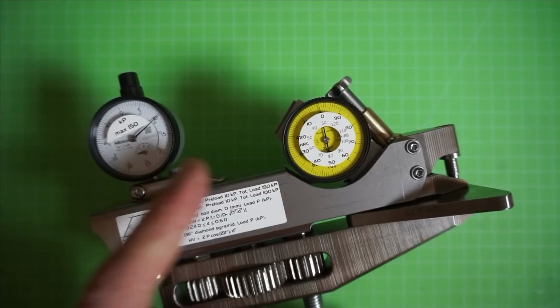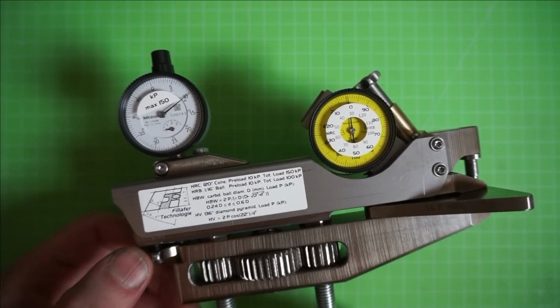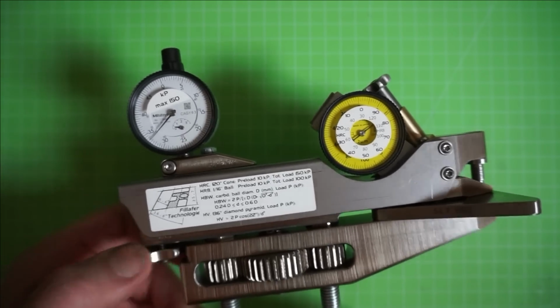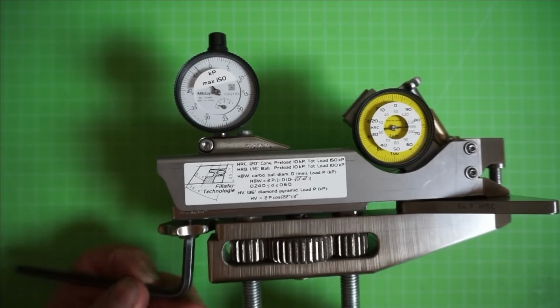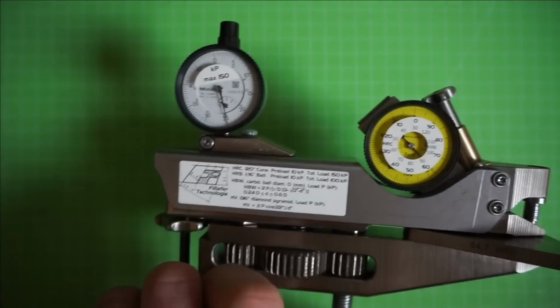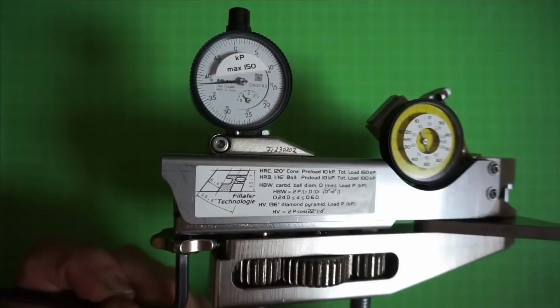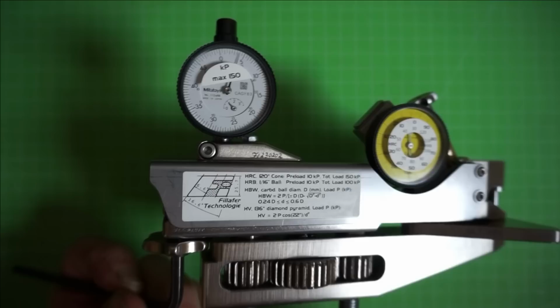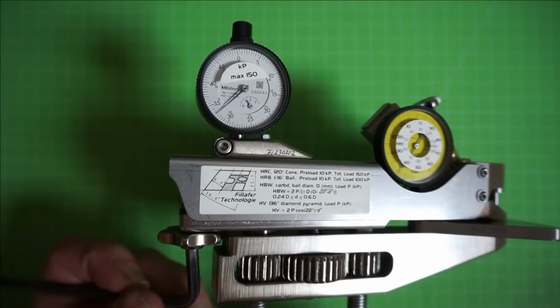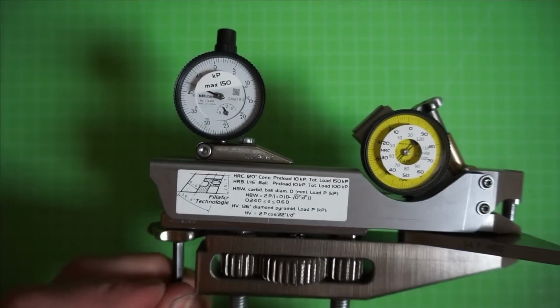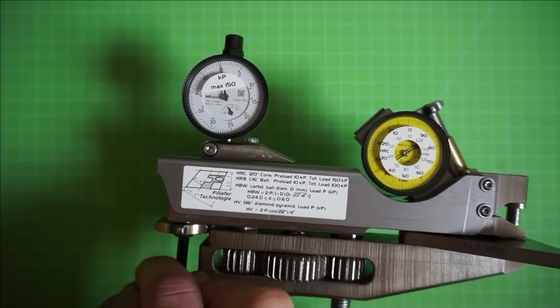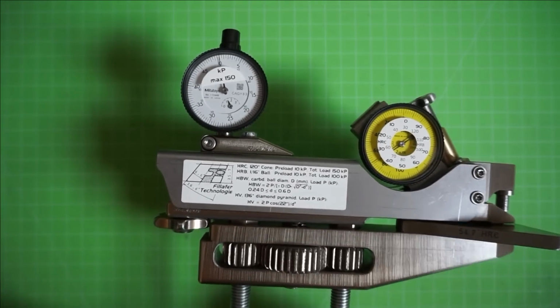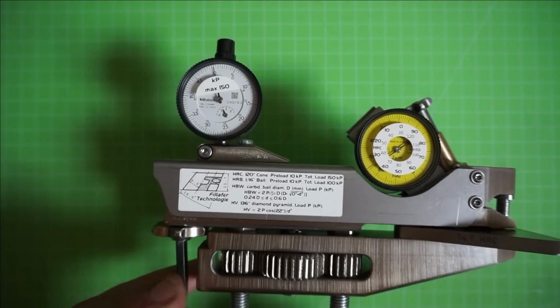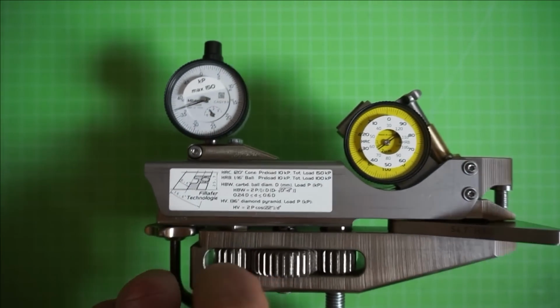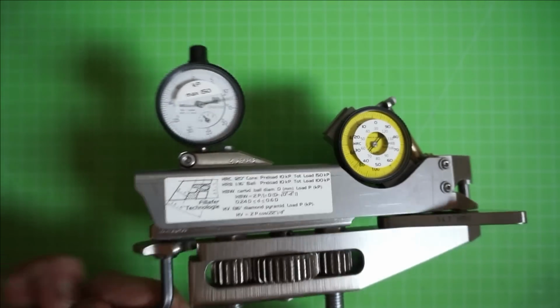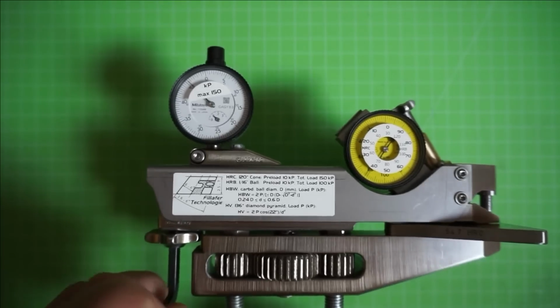Alright, so preload is on. Depth measurement is zeroed, and now we put in the test load of 150 kiloponds. I'll do this with this Allen key here. So that's 100 and 150. You already see on the second indicator that we sunk into the surface already, of course. So 150 kiloponds, that is. Now we have a holding time of 4 seconds as per ISO standard for Rockwell measurements. And now we relax the load on the indenter back down to the preload of 10 kilograms, or 10 kiloponds.